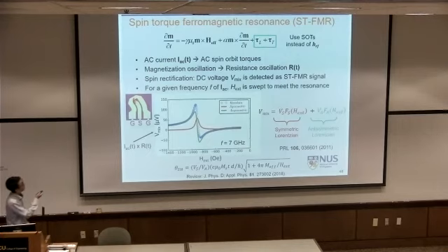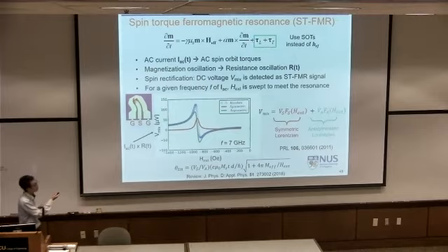The established method is spin torque ferromagnetic resonance. So on top of conventional FMR, we have these 2 additional torque terms. One is longitudinal and the other one is transverse torque term due to SOT. Then once you measure the DC rectification voltage as a function of magnetic field, you have the rectified DC voltage, which we can decompose into symmetric and anti-symmetric components. And basically the intensity of those two can be compared, and then you can extract the spin Hall angle value.